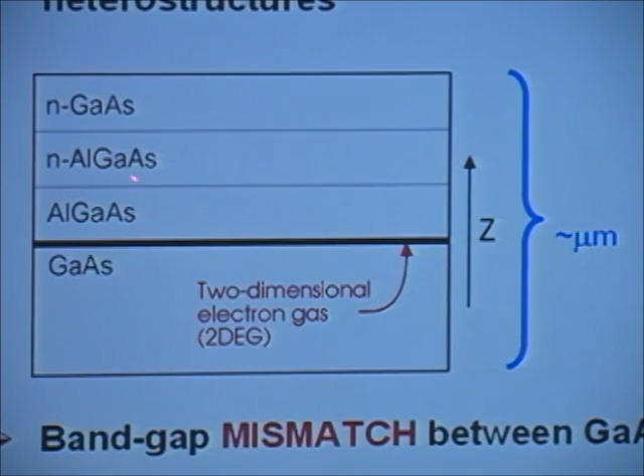Now what happens is, this is doped N-type, and the electrons from here fall down into the gallium arsenide. And this layer here is undoped completely. What this means is that the electrons, which form a layer against the interface, can't get back into the aluminium gallium arsenide. They don't have the energy. And there's a distance of several hundred angstroms between these electrons and the dopants which give rise to them.